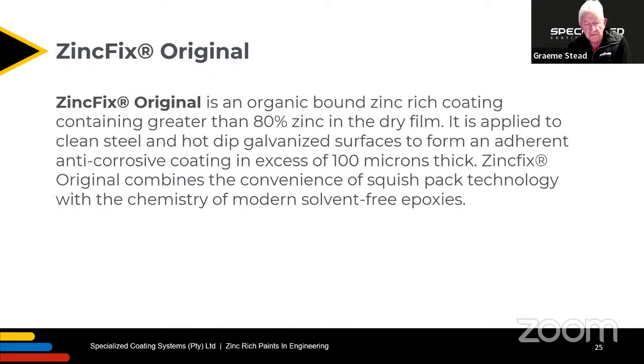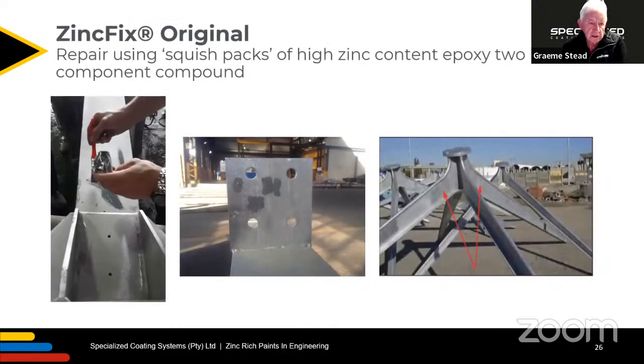But this has been a very, very successful product and is used extensively in the galvanizing industry. We have literally sold hundreds of thousands of units of this product. And this is it in use. We supply it in 100-gram packets, which is only about 30 milliliters, and that is about all you can apply from a packet in that short time. The galvanized items out of the zinc bath always contain scratches and things from the hooks that they pull in and out and guide the stuff off the cranes with. If you left them, they would form rust spots. And ZincFix has solved that problem to a great degree.